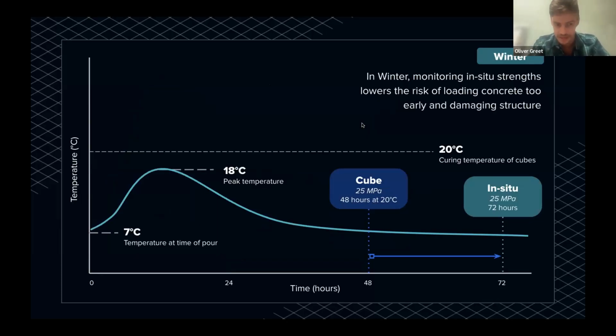I'll take now a winter case. So we're pouring concrete at a temperature of 7 degrees Celsius. And as a result, it doesn't actually give off quite as much heat, and it never quite goes over its 20 degrees Celsius threshold at which we're curing our standard condition cubes. Now, in this case, the cubes will obtain 25 megapascals at 48 hours, but this is a slightly artificially accelerated picture of the true strength development.